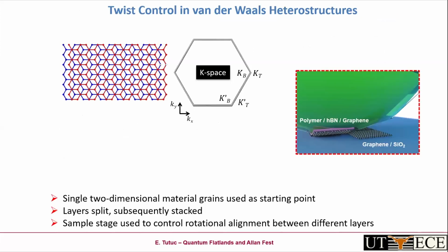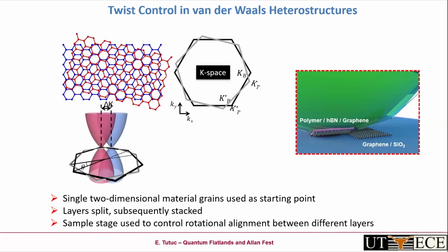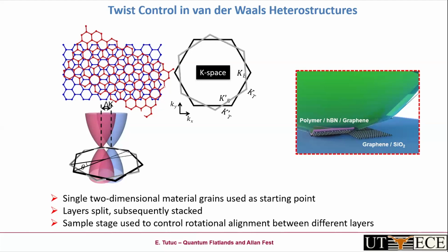And the way we would do it experimentally is to align the layers in real space, because aligning them in real space would align the Brillouin zones in momentum space, and that would ensure that the electron momentum is a good quantum number and is conserved in tunneling. Okay. So the technique is, in hindsight, a straightforward one.